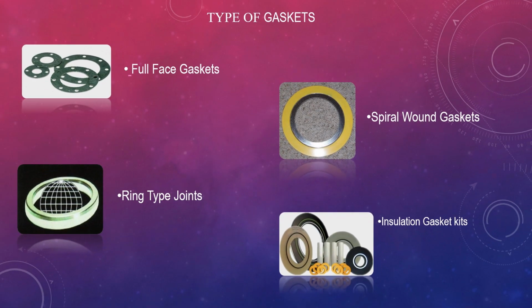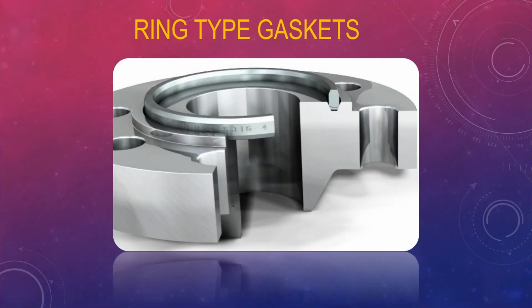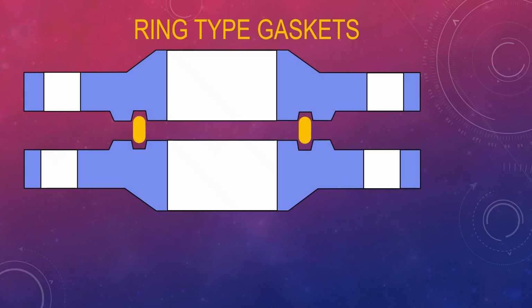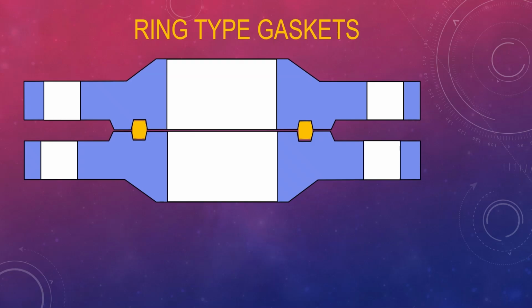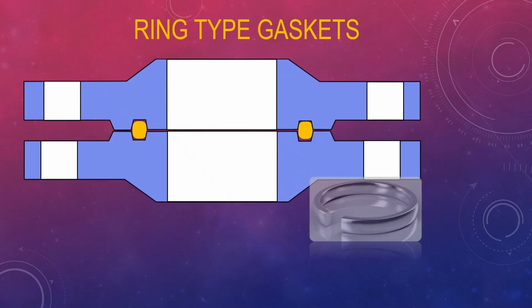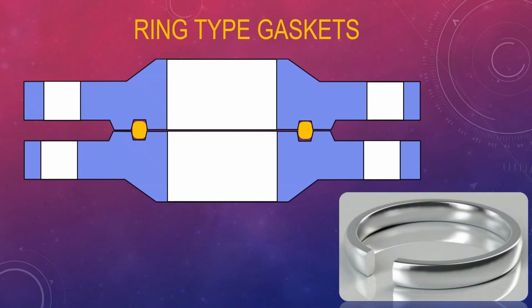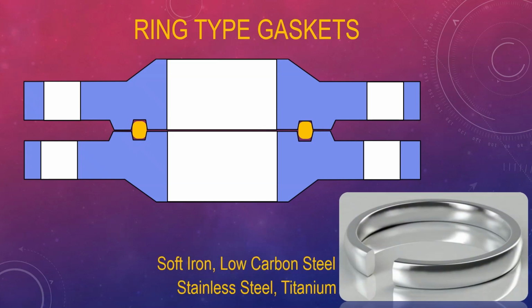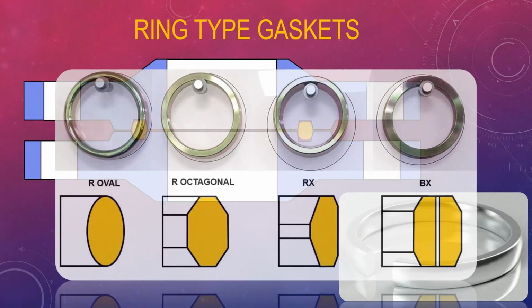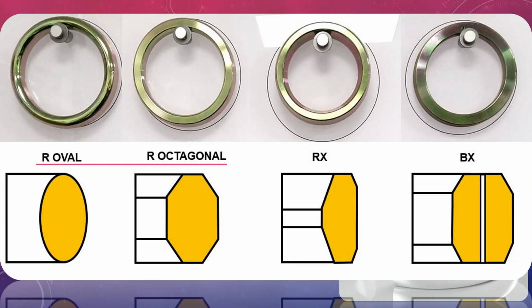What is the fundamental, non-negotiable material rule here? This is critical and purely mechanical physics. The RTJ's functionality relies on the softer metal of the gasket being compressed into the groove of the harder flange material, allowing it to flow and form a perfect seal. Ah, so it has to be softer. The absolute rule is that the gasket material must always be softer than the mating flange material. We see three main types: type R, oval or octagonal, type RX, interchangeable with R, and type BX, which is designed for the highest pressure systems where the two flange faces actually touch.